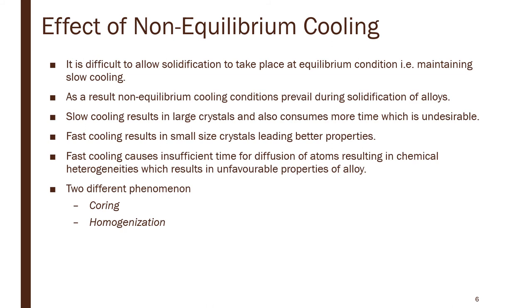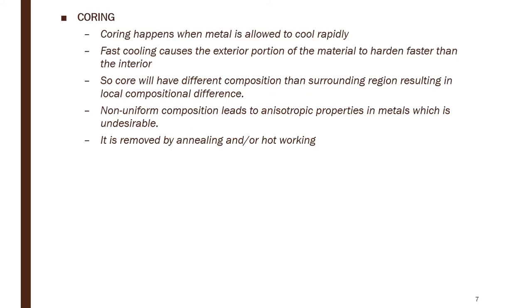and let's discuss that in detail. The first one is coring. Coring, or dendritic segregation, happens when a heated metal is allowed to cool rapidly. Rapid cooling causes the exterior portion of the material to harden faster than the interior, that is the core. As such, the core region will have a certain composition, while the surrounding region has another composition, thereby resulting in a local compositional difference. So usually the grains in the core region consist of a structure with higher melting temperature elements. The non-uniform composition produced by non-uniform solidification leads to anisotropic properties in metals, which is undesirable.